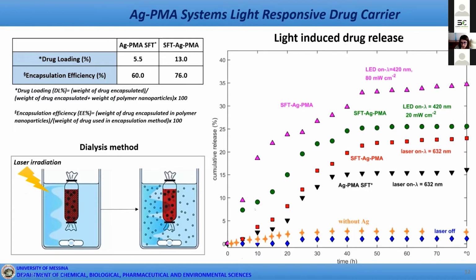And in the first stage of the drug release process, we can also observe a linear correlation between the cumulative amount of drug release and the time. This demonstrates the key role of silver nanoparticles to reach a spatial and temporal and drug dosage control.